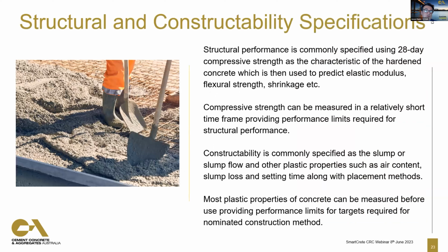From a structural and constructability specification point of view, we have some very simple tests that we do in regards to the hardened concrete, typically strength, which can be used to predict other properties such as stiffness, modulus, flexural strength or shrinkage or otherwise. It's a very simple test. It's typically tested at 28 days. There's an opportunity to change that test date to a later date, take advantage of maybe 56 days where it's appropriate, and take advantage of the strength gain we get past 28 days that doesn't occur that much with straight cement mixes, but occurs highly with SCM mixes.